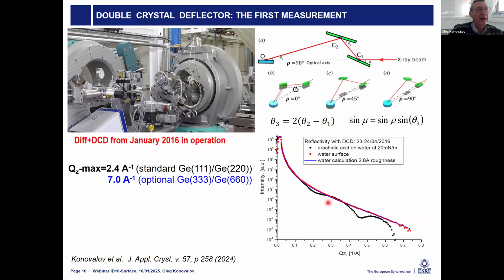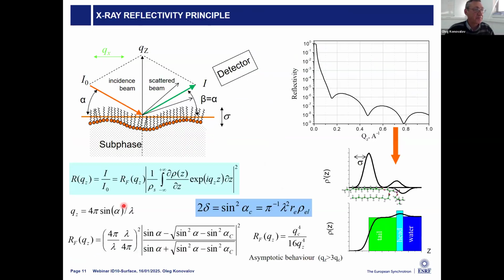Okay. And so for this system, we can work with two setups. One is basic, what we call standard. This is this pair of crystals which deflect the beam, and then we can go up to 2.4 reciprocal angstrom. But recently, we learned how to use the same crystals and go to higher reflections, 3 times higher for each of them, and then we can expand the QZ range on liquid surfaces up to 7 reciprocal angstrom. So, which could be a very interesting option for people who work on liquid metals, for example.